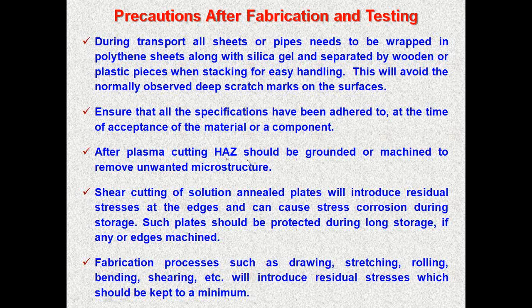Plasma cutting. After plasma cutting, heat affected zone should be ground or machined to remove unwanted microstructure. Shear cutting of solution annealed plates will introduce residual stresses. Such plates should be protected during long storage. Fabrication such as drawing, stretching, rolling, bending, shearing, etc. will introduce residual stresses. These should be kept to a minimum.